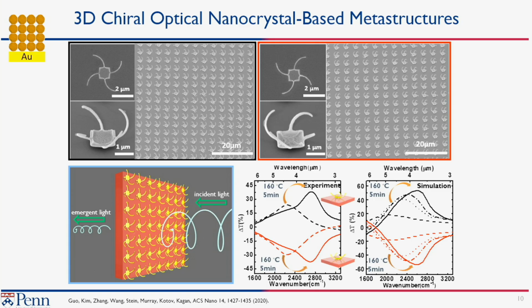And then we could build these processes over large areas, and each one of these structures would fold. To characterize these over large areas, we would prepare circularly polarized light. If the handedness of the circular polarization matched the direction of the folding of the arms, then you'd expect the transmitted light to be reduced. And if you had the opposite handedness, then it wouldn't reduce the transmitted light by as much. So the characteristic that we look at is how different the transmission of light is when we illuminate with right versus left-hand circularly polarized light. And that's what we call delta T.